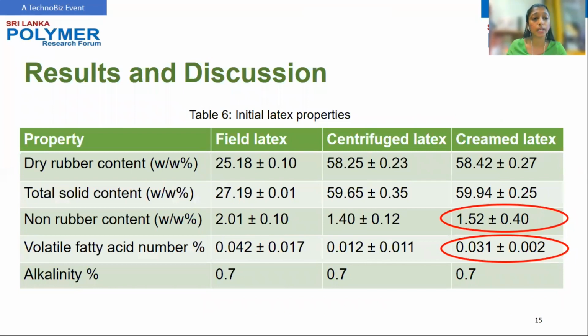However, lower non-rubber content suggests that in addition to water, part of the non-rubber substances were removed with both latex concentration methods. Cream latex has high non-rubber content compared with the centrifuge latex. Hence, the volatile fatty acid number of cream latex is somewhat higher than the centrifuge latex. When we consider the alkalinity, both centrifuge latex and cream latex decreased with time due to the evaporation of ammonia. So, alkalinity was maintained at 0.7 on latex.